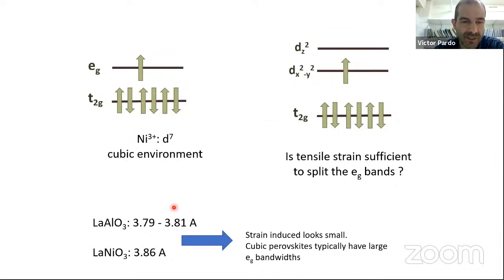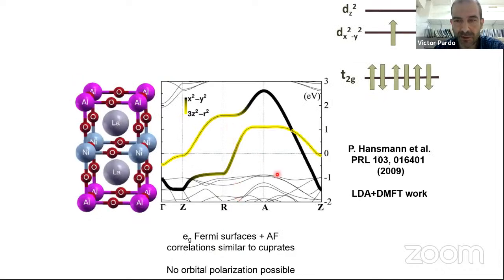However, when you go to experiments, the actual strains that you can introduce with typical substrates like LAO are very small. And what you see from calculations, for example, this one from Philipp Hansmann, is that if you look at the band structure, yes, the bands are somewhat split, but the bandwidths are very large, and you never get a large orbital polarization around the Fermi level. You never get a single band picture like in the cuprates. So this one is not a good example to pursue.